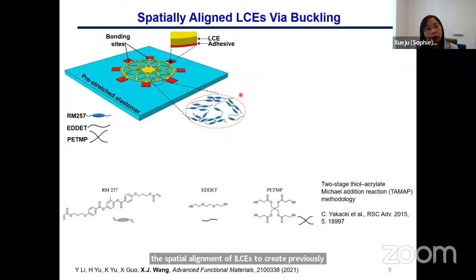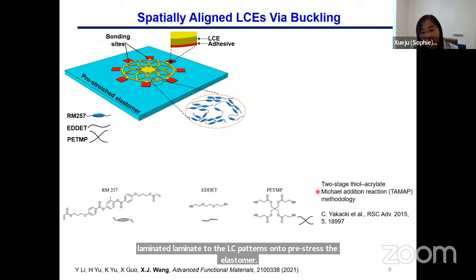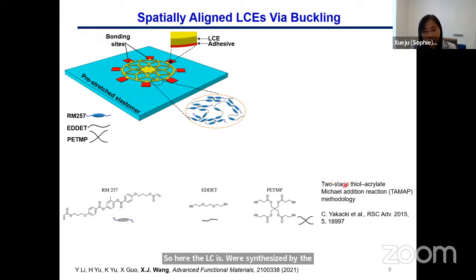This is based on a so-called compressive buckling technique that was originally developed by Zhang, Yonggang, and Yihui a few years ago. Basically, we first laminate the 2D LCE patterns onto a pre-stretched elastomer. Here, the LCEs were synthesized by the classic two-stage thiol-acrylate Michael addition reaction methodology because of its ease of use and also its reliability. We applied a thin layer of adhesive between the LCE and the elastomer substrate at selective locations to create strong bonding sites.